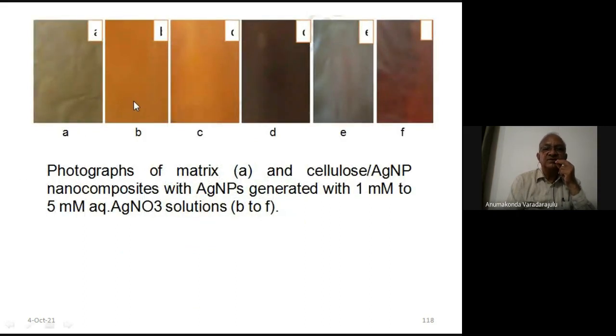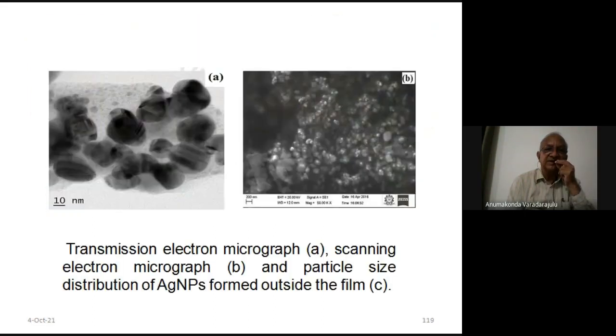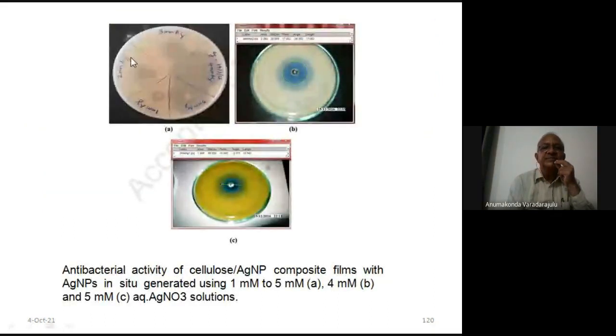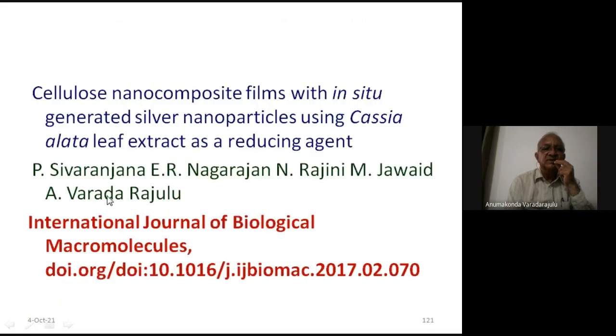So this is the cellulose matrix, and these are the composites with silver of different concentrations. The color change indicates the formation of the nanoparticles inside the matrix or inside the composite. This is the TEM picture and this is the SEM picture. So beautiful spherical nanoparticles are formed. And this is the antibacterial activity. So this also showed very good antibacterial activity. We published them in 2018, 3 years back. If somebody is interested for additional information, you can go through this publication.